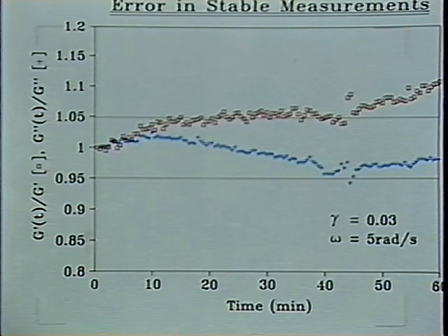The stability is not as nice as we are used to in conventional polymeric liquids, but it's pretty nice. And when you look at data in the literature, stability has been a problem in many data. The sample has been unstable. If you perform experiments, say at 310, as we saw in the literature, even higher, the sample changes, and you have all kinds of additional phenomena coming in. Susan wanted to exclude that and performed experiments at low temperature because of that.